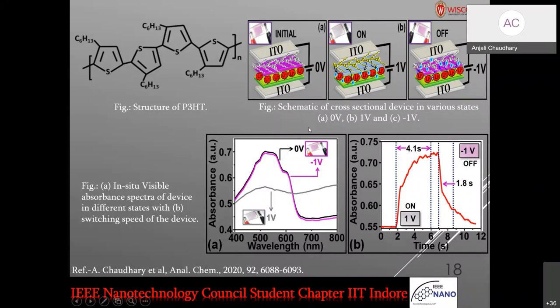And to quantify its color change using UV-vis spectroscopy, we have found that initially this black curve is at 0 volt. It absorbs maximum wavelength at 520 nanometer. That's why it appears to be magenta. And this absorbance can be easily understood according to the previous figure that I have explained. And when you apply 1 volt, in the gray curve, it nearly absorbs all wavelengths, and it appears to be transparent to our eyes. And when you again apply minus 1 volt, it regains its initial magenta color.